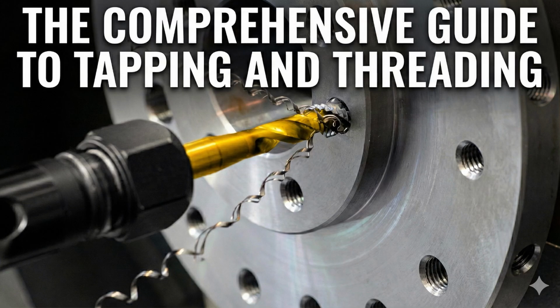And finally, let's circle back to the forming tap. We established it's chip-free, but what dictates if a material can be formed versus having to be cut? The material must be ductile. That's the key. It has to be able to deform plastically without cracking. So we're talking soft steels, some stainless steels, aluminum. Right. The material properties are everything. If the material is too hard or too brittle and you try to form it, you'll just shatter the tap and ruin the part. But when the material is right, the benefits are incredibly compelling. We mentioned the strength increase earlier.